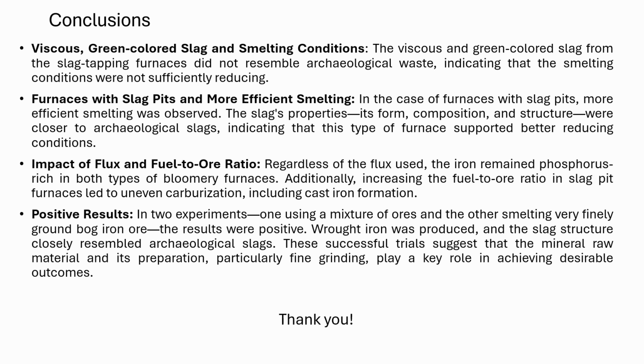Regardless of the flux used, the iron remained phosphorus-rich in both types of furnaces. Additionally, increasing the fuel-to-ore ratio in slag pit furnaces led to uneven carburization, including cast iron formation. In 2 experiments, one using a mixture of ores and the other smelting very finely ground bog iron ore, the results were positive. Wrought iron was produced and the slag structure closely resembled archaeological slags.